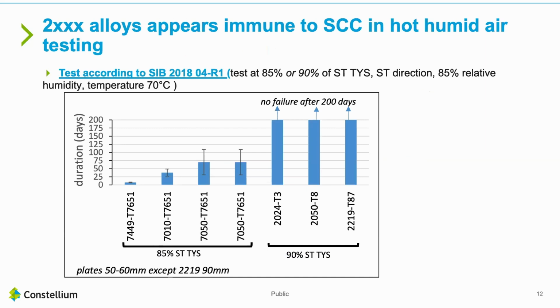We have compared 7,000 series to 2,000 series, and it appears that 2,000 series, so 2024 in T3 temper without aging, 2050 and 2219 in T8 temper, so at peak aging, have no failure after 200 days, so they are quite immune to stress corrosion cracking in hot humid air.